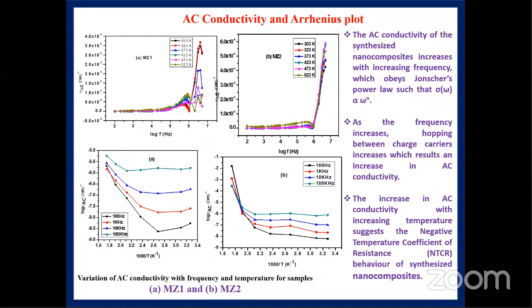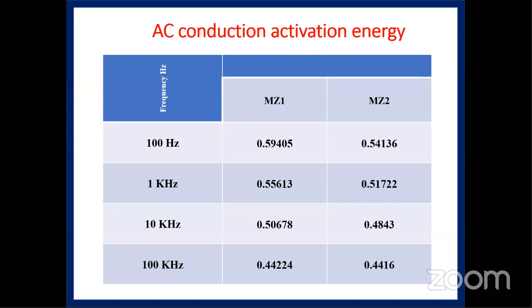AC conductivity also increases with increasing frequency and with increasing temperature. From this Arrhenius plot, we calculated the activation energy of these different ratios of the nanocomposite, MZ1 and MZ2, at different frequencies: 100 Hz, 1 kilohertz, 10 kilohertz, and 100 kilohertz. You can see here that the first ratio of the sample is quite higher when compared to MZ2.